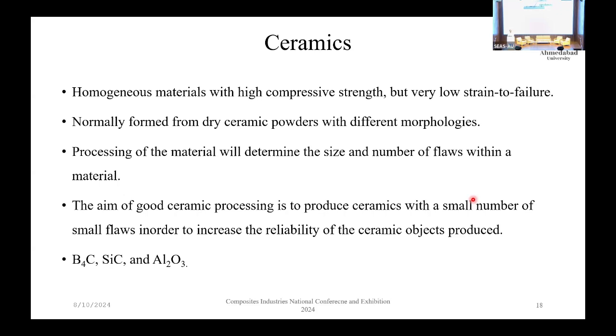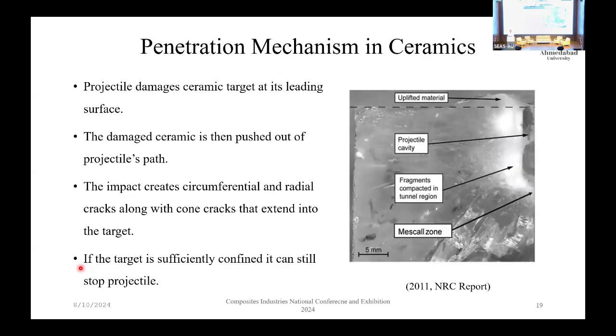in the material. The most commonly used materials for this case are boron carbide, silicon carbide, and to some extent aluminum oxide as well. Presently, the cost efficient solutions comprise a hybrid of boron and silicon, because boron is very costly and silicon is slightly less, but the density of silicon is slightly higher than boron. So it's a compromise between the cost and the technology. If you want to go for the best possible solution, go with boron carbide, but then the cost is the highest possible. And many studies were done to see how the penetration happens in this case.